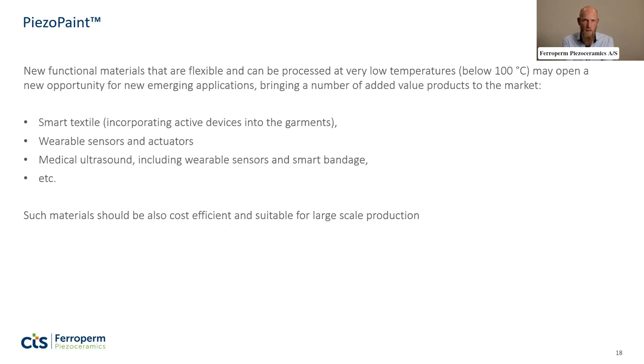And we did see a call in the market for this kind of application space where we wanted to incorporate piezoelectric materials into textile or other garments in order to make wearable sensors and actuators. Also, we identified applications within medical ultrasound to integrate devices or print film on patches, or having wearable sensors where you had to have some kind of flexibility as well. So two things are necessary to accomplish that. One is, of course, the firing temperatures and the processing temperatures have to be low enough so the substrates can survive, and you need some flexibility in the material, which is not present in a ceramic.